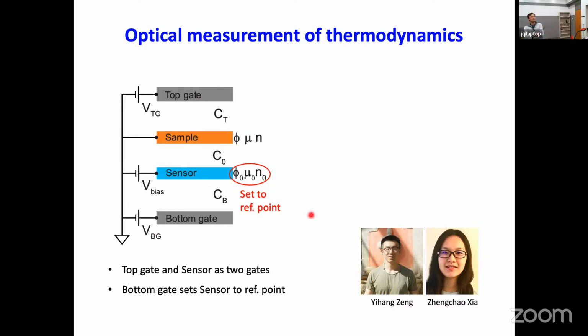So this is our device structure, which is a little more complicated compared to the previous device. We have our sample of interest here, and we also have top and bottom gates. All those white space regions are just boron nitride. In addition to the top and bottom gates, we also put a sensor in between the bottom gate and the sample. The function of the sensor is that we vary the bottom gate voltage to fix the sensor to a fixed reference point.